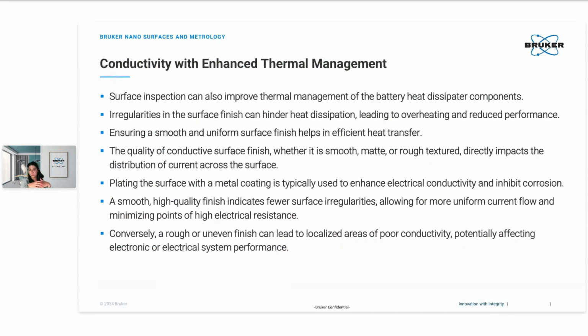The quality of conductive surface finish, depending whether it's smooth, matte, rough, roughly textured, directly impacts the distribution of the current across the whole surface. And most of the time, plating the surface with a metal coating is a very typical way to enhance the electrical conductivity and to inhibit also corrosion. So a smooth, high quality finish indicates always fewer surface irregularities, also allows you for more uniform current flow, and minimizes the points of high electrical resistance.